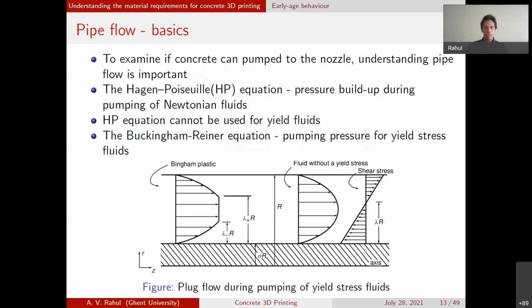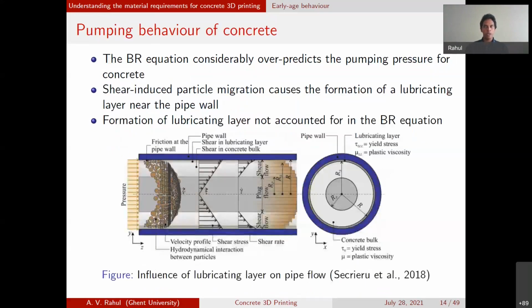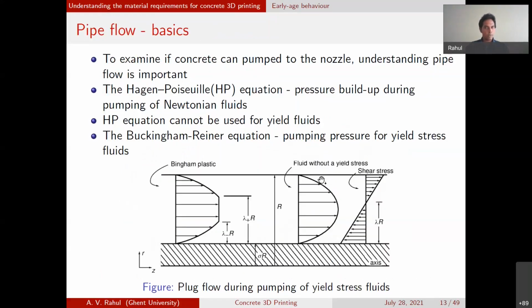But now, when you talk about concrete, there's one more complication that arises, which is the formation of a lubricating layer. This Buckingham-Reiner equation is a general equation that's valid for all Bingham fluids, all yield stress fluids. So if you're doing this analysis, say with toothpaste, you will get a very good result. In fact, if you experimentally measure the pressure, and if you do the theoretical calculation for the equation, you'll see that you get a very close match.